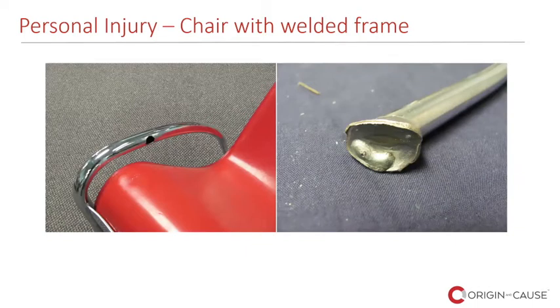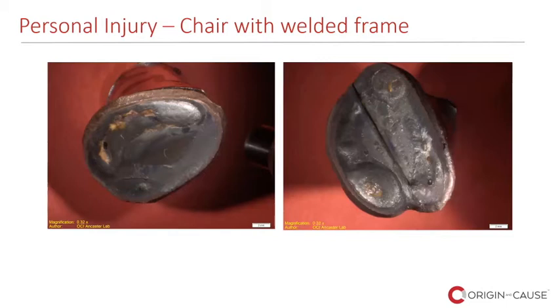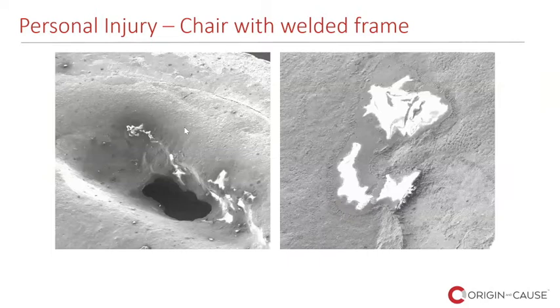We documented the frame and the welds, and we took them for examination under the stereo microscope and later to a scanning electron microscope. The bars with the two failed welds are shown in these images, and one can see that the welds contain large porosity and inclusions. They are undesirable because they act as stress concentrators and they decrease the load carrying capability. One of the welds was taken for examination under the scanning electron microscope, which confirmed the presence of large pores and non-metallic inclusions. As I said, these deficiencies are significant because they act as stress concentrators and they reduce the load carrying capability of the weld.